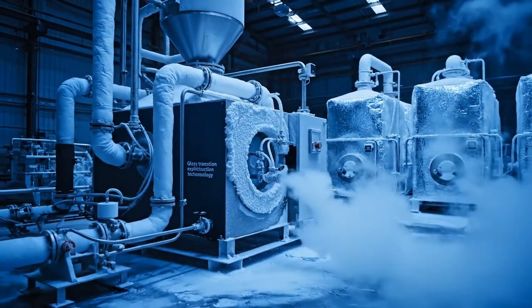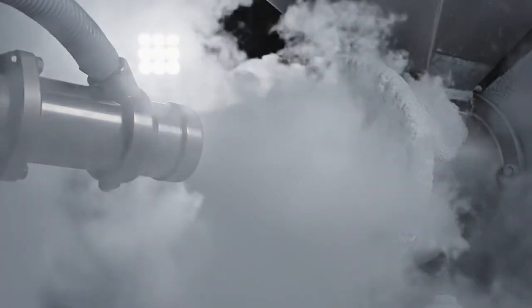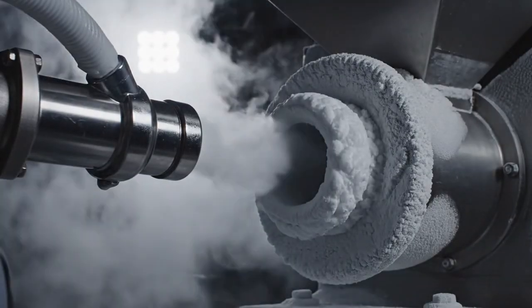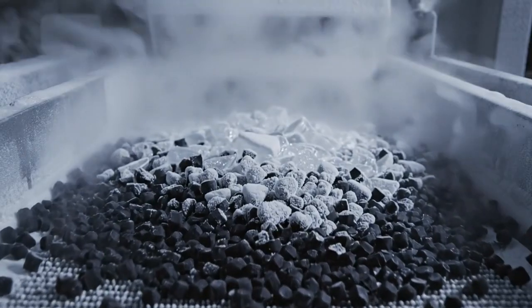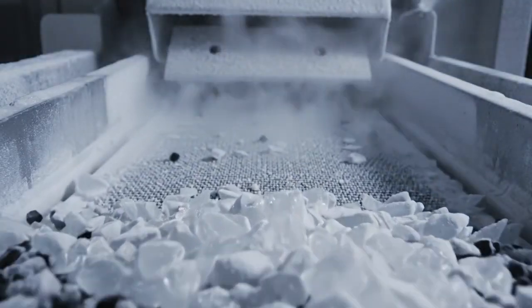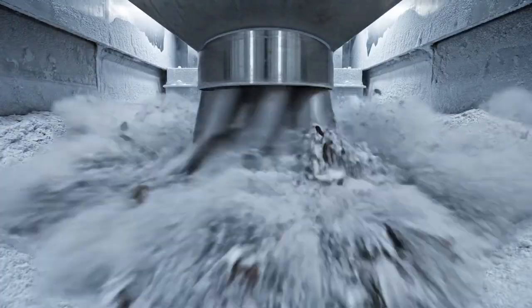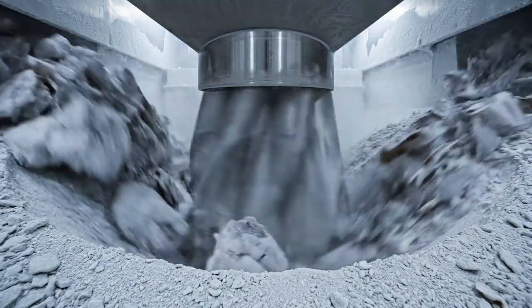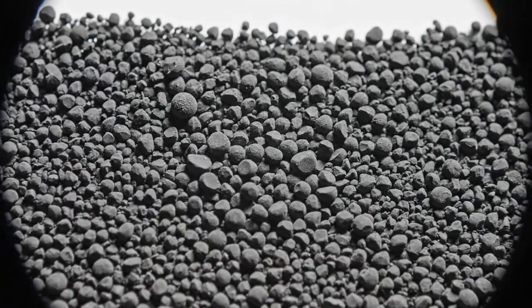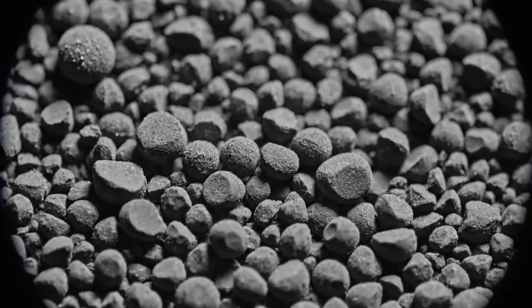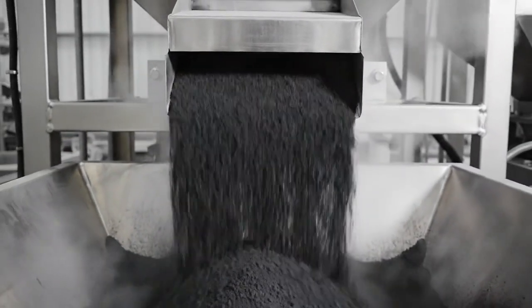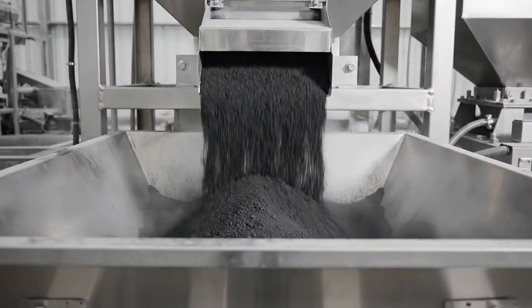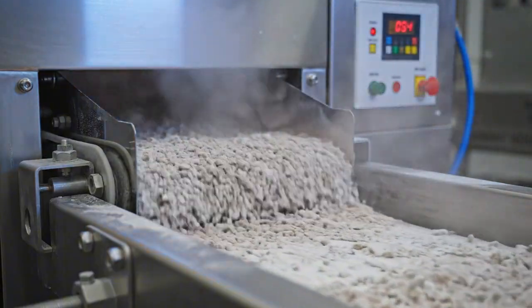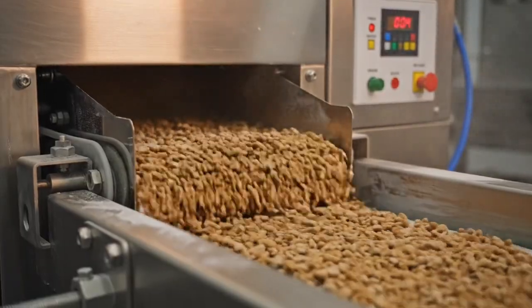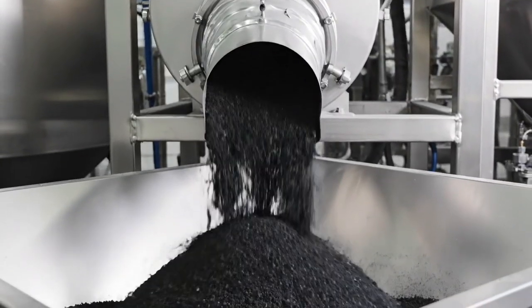The sorted rubber stream proceeds to cryogenic grinding, a process that exploits the glass transition temperature of elastomeric materials. Liquid nitrogen at minus 196 degrees Celsius is injected into the grinding chamber, flash freezing the rubber particles until they become brittle and glass-like. In this frozen state, the material can be pulverized to extremely fine particle sizes impossible to achieve at ambient temperature. The cryogenic mill's rotor, spinning at 3,600 RPM, impacts the frozen rubber with kinetic energy sufficient to fracture it into particles measuring 200 micrometers in diameter, fine enough to pass through a 70-mesh screen. The process is energy-intensive, but essential for creating rubber powder of sufficient fineness for reincorporation into new manufacturing processes.